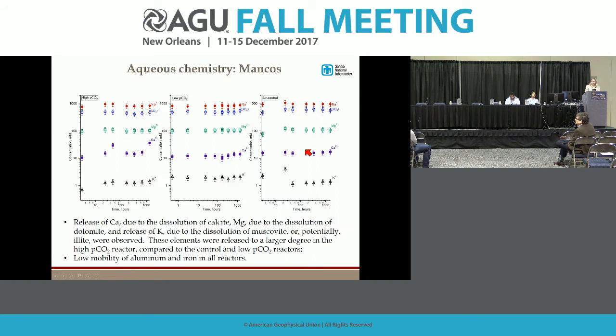And these are aqueous chemistry results collected from different reactors. I'm showing high pressure CO2, low pressure CO2, and one of the control reactors. We always run a control just to make sure we know what's going on when there's no CO2 in the system. And the changes here are really subtle. Remember, I mentioned that we started with a concentrated complex brine as close as possible to being in equilibrium with the shale. So our changes are subtle, but they're measurable.